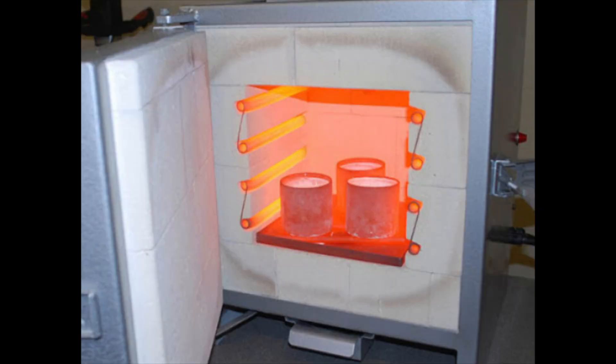When you pull the bottom off the can, you can see the cone shape and the rod leading down to your model. Here's how the process works: you put holes in the can, then put it in a kiln at 1,350 degrees for an hour or two. All the wax melts out — it actually vaporizes, and the smoke comes out. Casting waxes are poisonous, so you don't want to be in the same room. The wax vaporizes and leaves its little shape — whether it's an insect or a car — and leaves its cavity in the plaster.